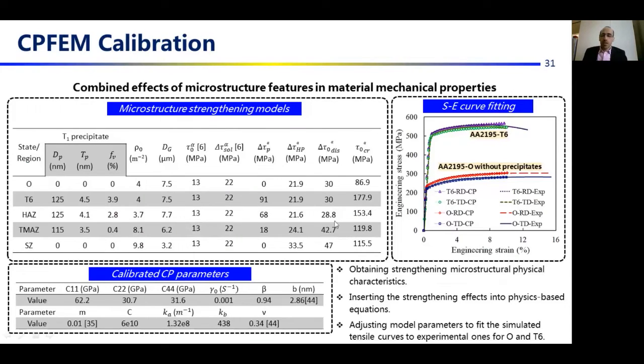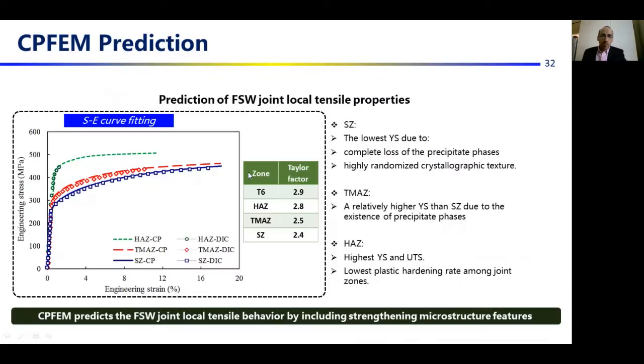CPFEM calibration includes obtaining the strengthening microstructural physical characteristics such as precipitates and dislocation density, inserting the strengthening effect into the physics-based equation to obtain the slip strengthening effect, and adjusting model parameters to fit the simulated tensile curve to experimental ones for the O-state material without precipitate and the T6 condition to fit the simulated and experimental tensile test.